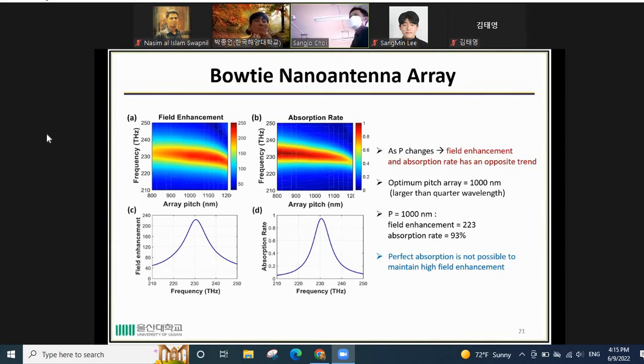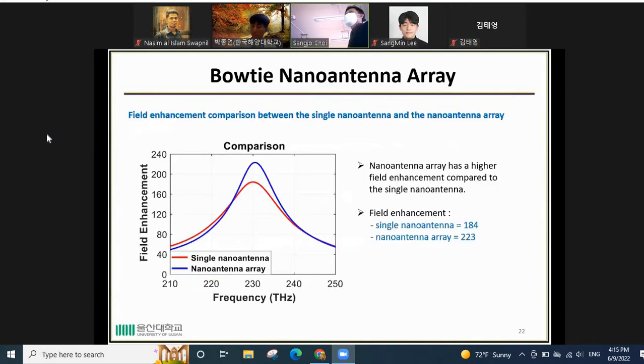We can see that it is showing field enhancement of 223 and 93% absorption rate. We can see also that perfect absorption is not possible using this design method, and also cannot maintain high field enhancement. So that's why,